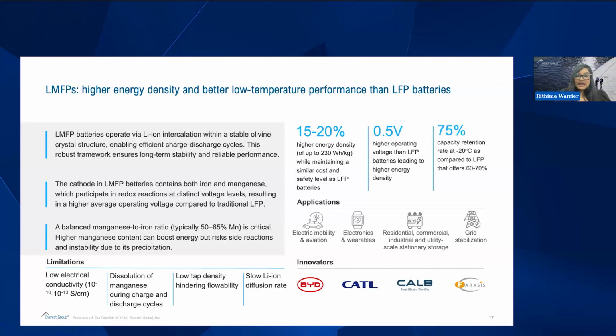This kind of jump, when combined with the stable olivine structure of the LFP batteries, offers a higher energy density of 15 to 20%. And it also provides 75% capacity retention at lower temperature as opposed to 60 to 70% in LFP batteries. It is important to note, however, that the manganese to iron ratio is very critical here. If you have a lower manganese ratio, below 50 to 65%, then it will be an underperforming LMFP. Whereas if you have more manganese than 50 to 65%, then it is going to risk side reactions.